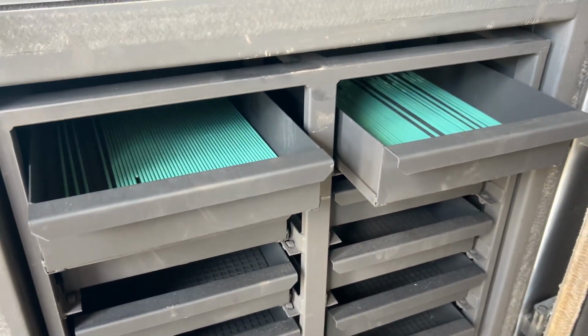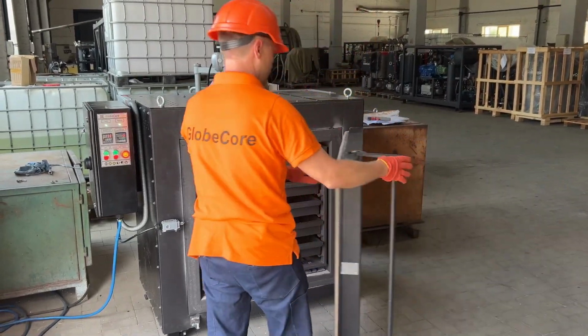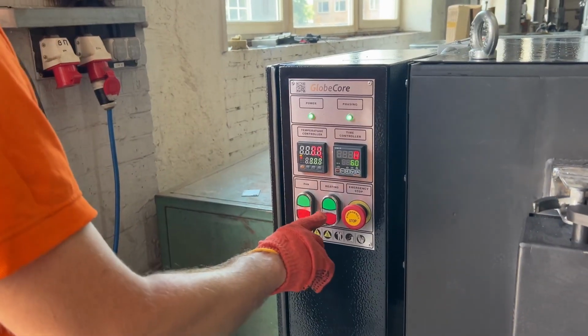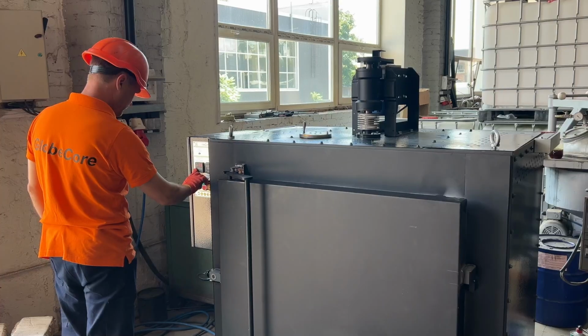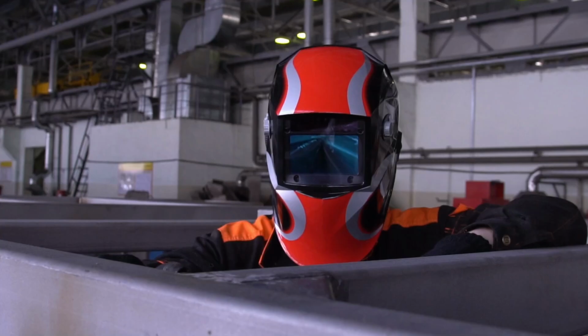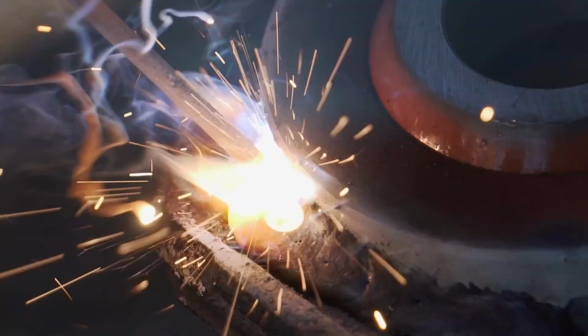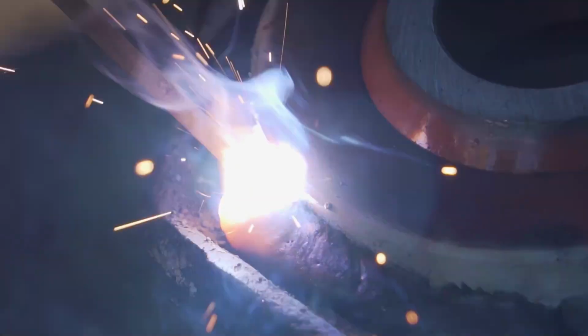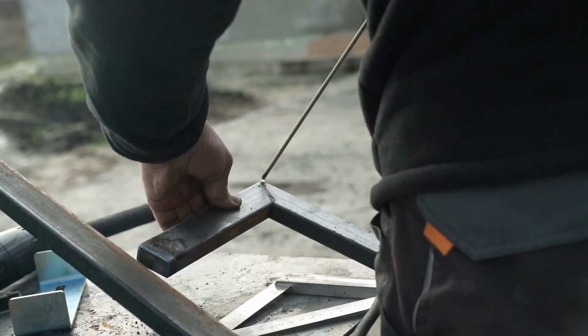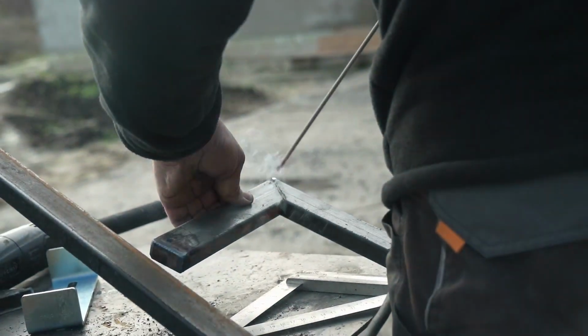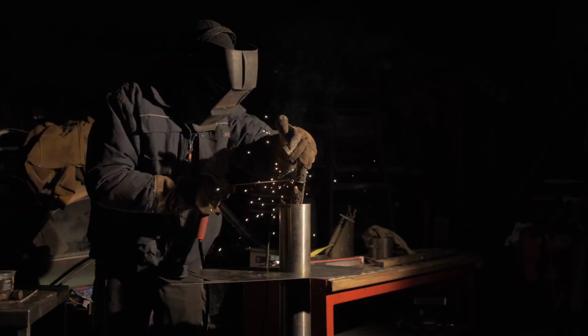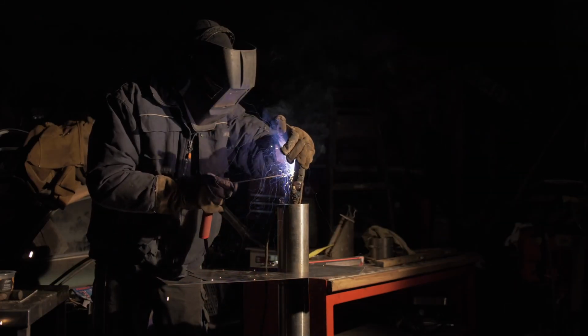Drying and calcination using the Globecore technology allows you to achieve the required operational performance of electrodes, to avoid sticking of electrodes, to ensure steady arc burning, to obtain the uniform and high-quality weld formation, to ensure high-quality primary and secondary ignition, and to restore the electrodes that have been impaired due to improper storage.